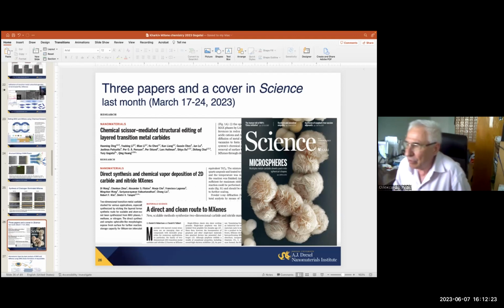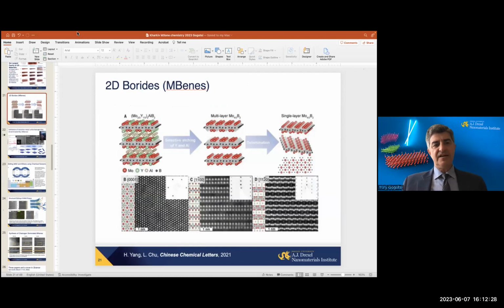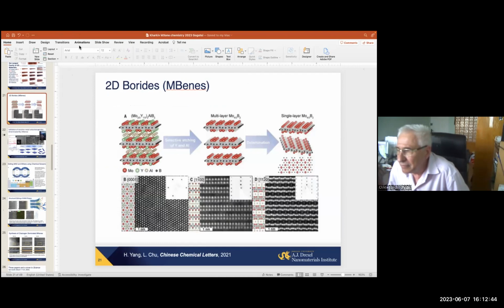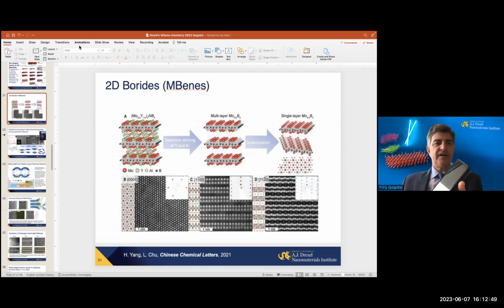Sure. There are a couple of differences here. One is, again, even spending more time than I wanted, I still didn't explain all the details. An MXene layer is basically a 111 slice of the cubic sodium chloride structure of conventional carbides and nitrides of transition metals. MBenes have a slightly different structure, so that's why they were kind of separated a little bit here. So the structural arrangement of atoms in the layer is different. But of course, they all have very different electronic structures and predicted different properties, semiconducting in some cases here.